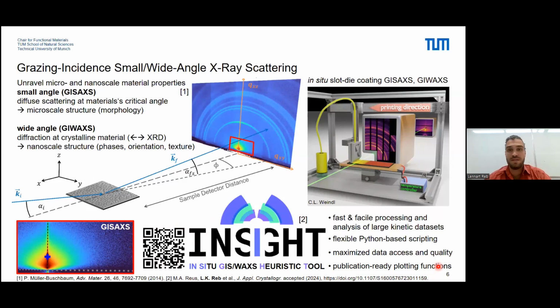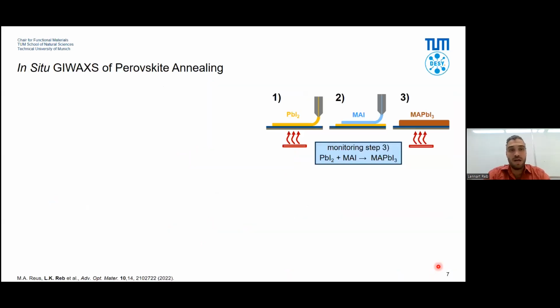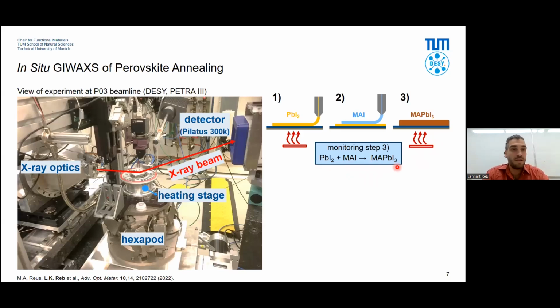So what can we do with these techniques? I'm giving you one example regarding in situ GIWAXS, in this case of perovskite annealing. So we have deposited a two-step perovskite film by slot die coating, and the third step, that is the interdiffusion during heating, actually creates the methylammonium lead triiodide perovskite film. And what we're doing is we monitor this step, and in the beam time at DESY, this can look like this. So we have the X-ray optics that creates the X-ray beam, basically lets it through, and then the sample is positioned here, and the scattered X-ray signal is registered by the detector. The sample is positioned on a heating stage, so we can heat the sample, and everything for alignment is on a hexapod so that we can align the sample in a proper way.